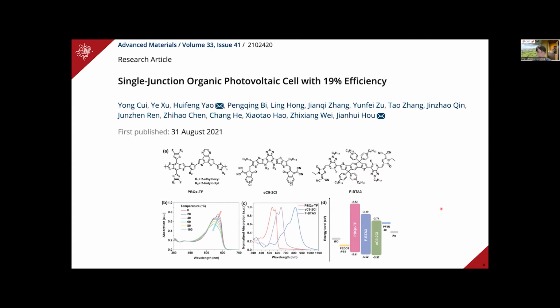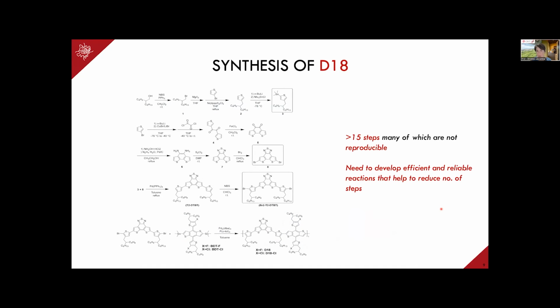And this complexity results in a difficult synthesis. So just as an example, on the following slide, I have the synthesis of a polymer known as D18. I have to admit, one of the problems in our field is that the polymer names are not the greatest, but this is a polymer that has been called D18. And it is a polymer that has resulted in very high performances. But you'll see that the synthesis is very, very long. It goes on and on and on. And if you count up the steps, it corresponds to 15 steps.